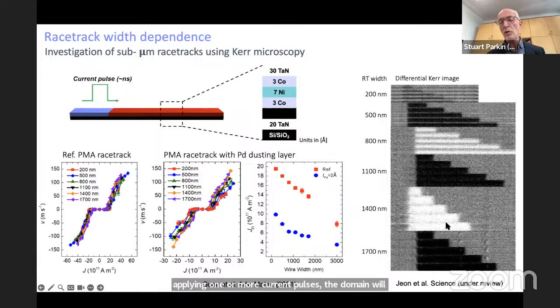And in this case, what we've done is we shrunk the width of the racetrack from 1700 to 1400 to 1100 to 800 to 500 to 200 nanometers. We can still see the domain walls in 200 nanometer wide racetracks, even though the wavelength of light is much larger. And then we could use this to determine the velocity.